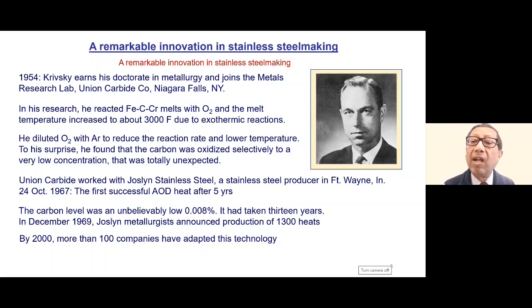So he found after one or two experiments that the temperature of the bath was shooting up to about 3000 degrees Fahrenheit because of exothermic heat. So what he thought is that this is not acceptable. He needs to maintain the temperature at a constant lower value.